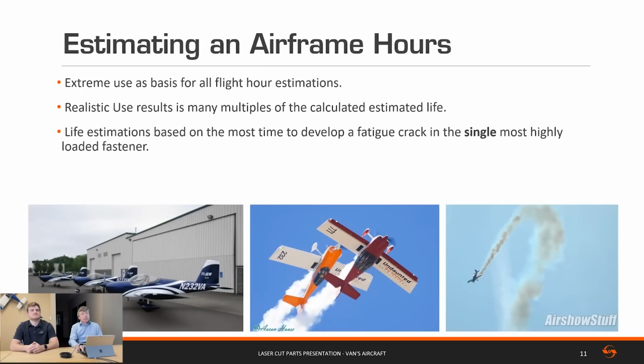Looking at how we developed the loads that we applied with the fatigue test machine and accelerated testing and used in our analysis, we went to a couple of different resources. AC 23-13A gives guidance on converting data back and forth between accelerated coupon testing and the real world. So we looked at it in two different segments, one for use in a flight school, and then we also looked at EFIS data from actual flights in aerobatic RVs. We use that EFIS data to come up with our own conversion curves in the same methodology used by the FAA. So we're using real world data to come up with real reduction factors.